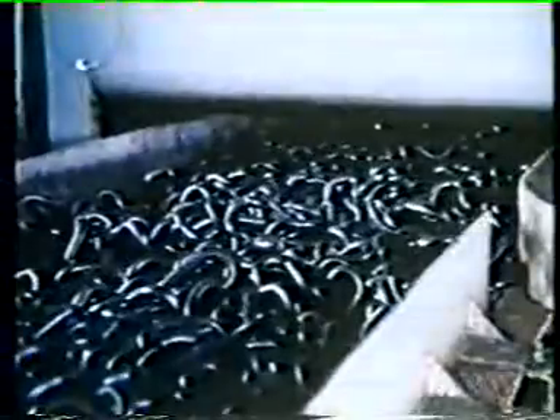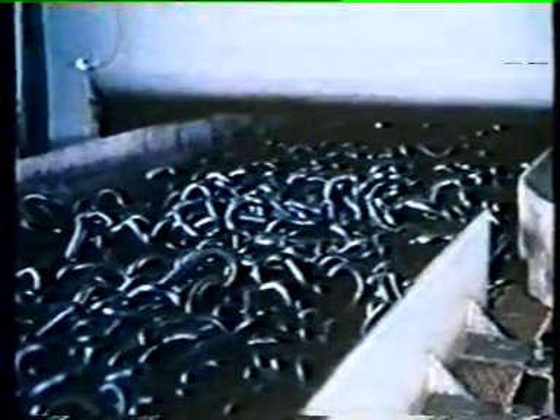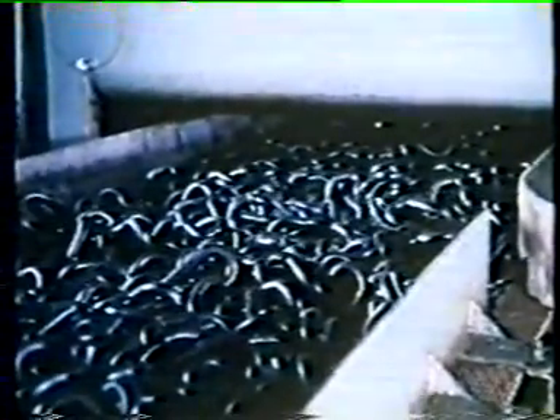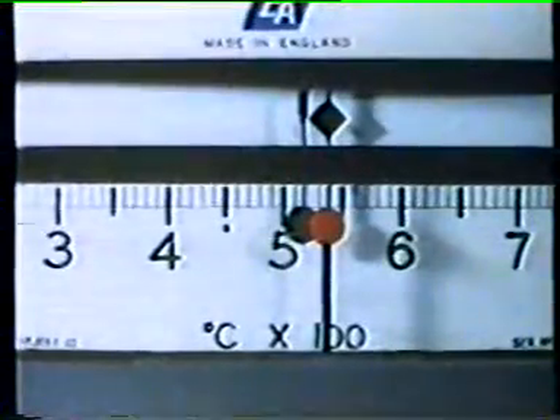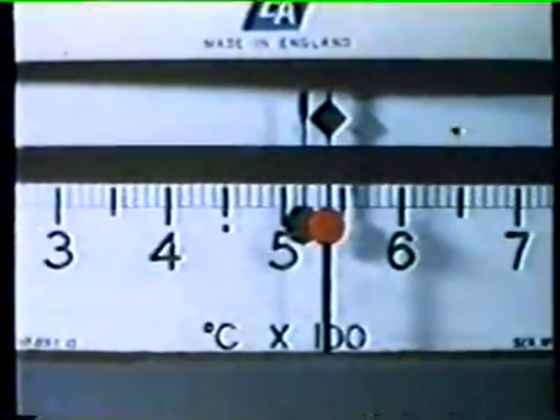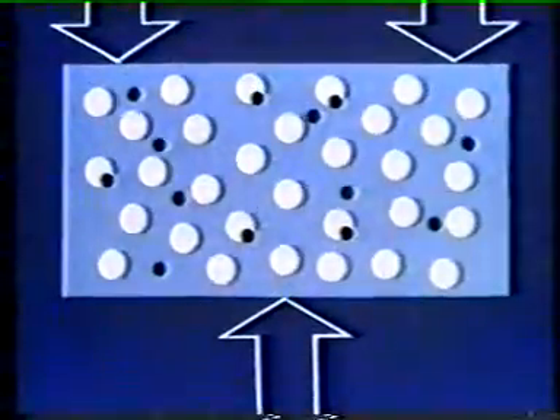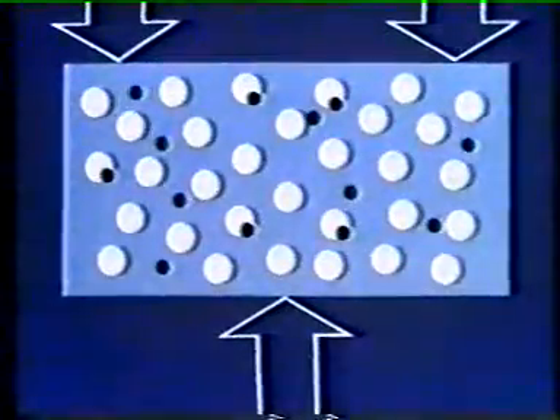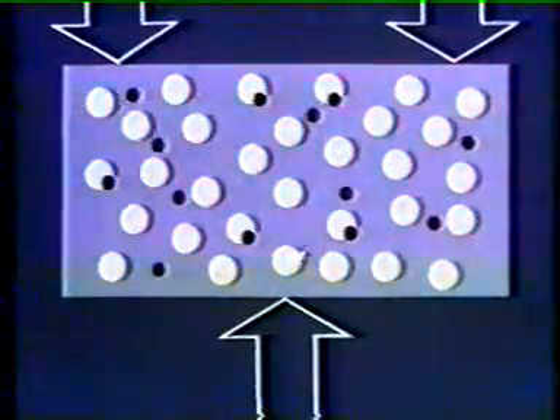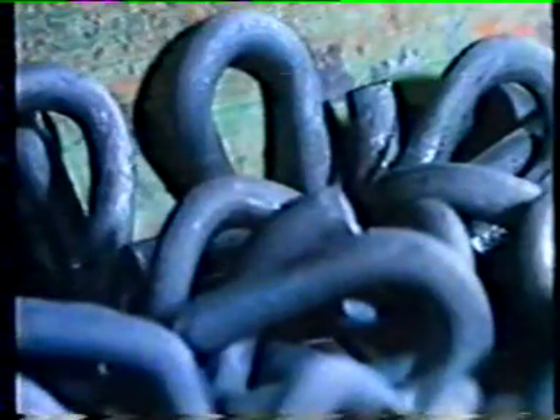So after quenching, into the tempering furnace for 1 hour. The temperature here is critical, 530 degrees centigrade. Brittleness of the martensite is relieved by the formation of cementite in scattered granules. The additional effects of the alloys are not shown here. After leaving the tempering furnace, the fasteners cool slowly in air and retain the properties induced by heat treatment. They are now medium hard with a high tensile strength, 85 to 95 tons per square inch.